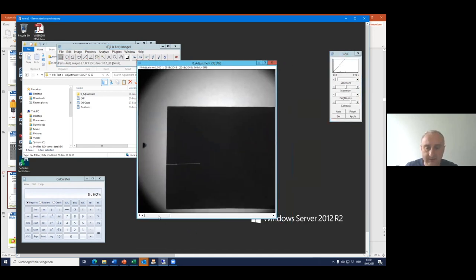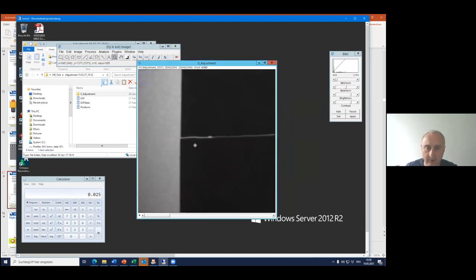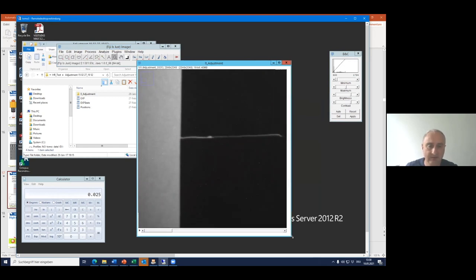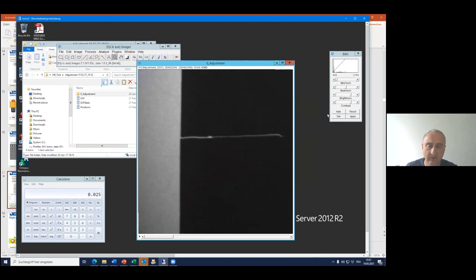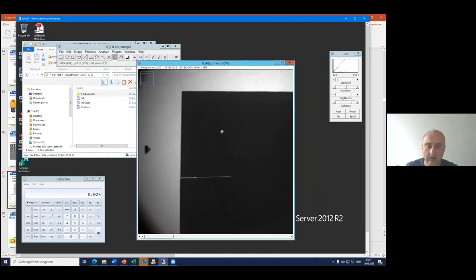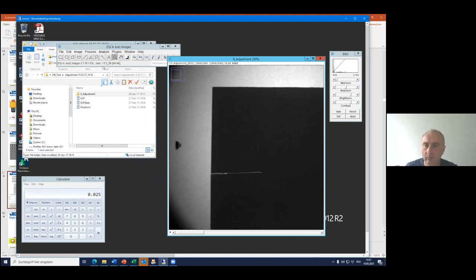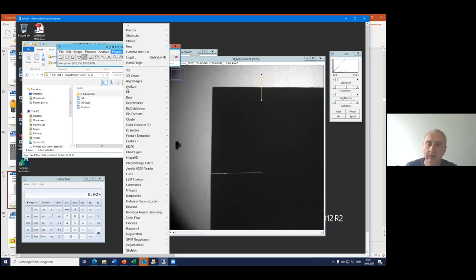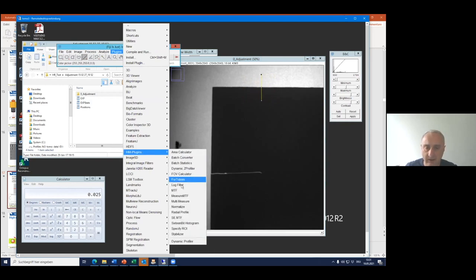What we can see here is that in the beginning we have a quite sharp image, and with the rotation steps, the image is blurred. So this means that there is some optimum at some position, but it's very difficult to estimate this by eye. Therefore, let's say we take one line profile. Here you see, we can take this line. And then we can use the MTF plugin.